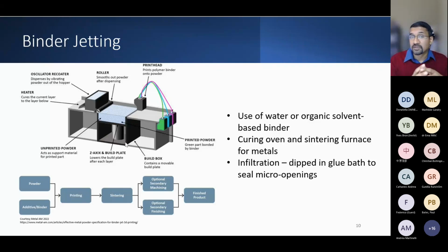The couple of key steps that are required to sinter it and make it into a full densified part is you bring it subsequently to a curing and a sintering furnace, curing to drive off the organic binders or water-based binders that you're using to densify, and then final densification is usually with sintering, right? So you have more than one set of process steps that need to happen.